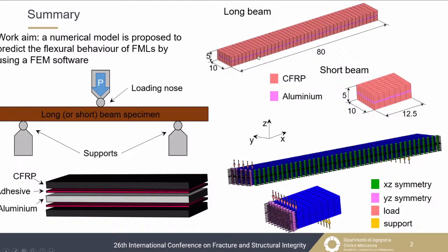As concerns the simulation, we considered only a quarter of the specimen for the long beam and a half of the specimen for the short beam. The mesh was formed by brick elements, 8-node linear brick elements. And the CFRP was simulated as a homogeneous orthotropic material, while the aluminum as a homogeneous isotropic material.